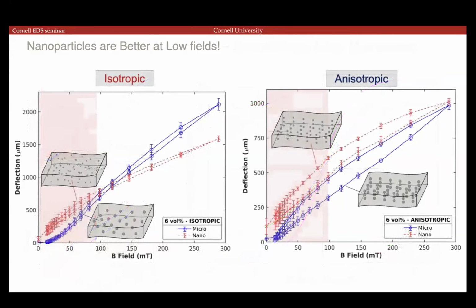I think one of the interesting things that we found in these materials is, if we back up a bit, in the beginning of the talk, I said nanoparticles have a bunch of edge effects, so they lose their magnetization at the edges. Also, when you scale it down, they tend to have a lower magnetic moment if they're randomized due to thermal fluctuations. In this case, our nanoparticles are actually deflecting more than the microparticles. So that must mean that the magnetization is better in some way.